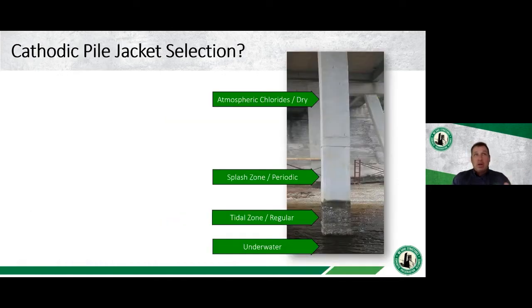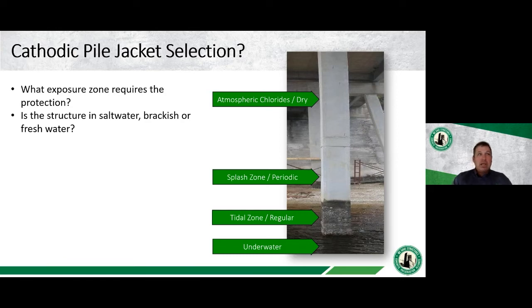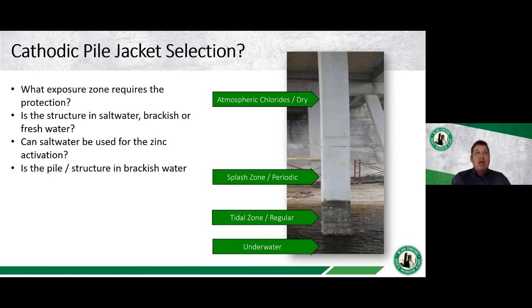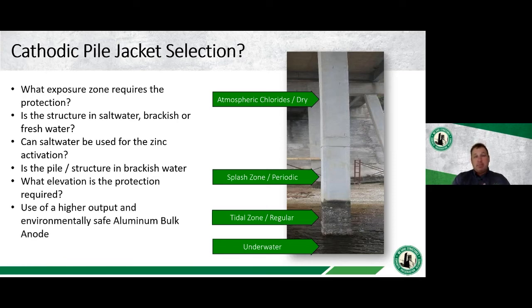Again, you can't just go in and select one jacket when you have a corrosion problem on a pile. You actually have to look at your environment. What are your exposure zones? Can you use salt water to activate the zinc? If you can't use the salt water, do you have to go to an activated jacket system? How high up are you going? Are you just trying to protect down low in the water column? Or are you going up to that atmospheric area where you have a lot of chlorides present, potentially corrosion, but you don't have access to the salt water? And then, can you use the aluminum bulk anode for a higher current output with the systems that are going to be used?